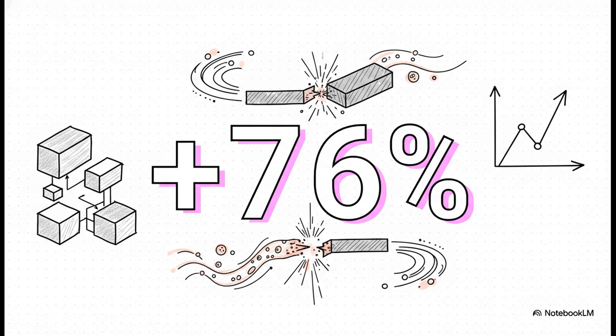In one study, researchers took 3D printed aluminum, used a very thin copper layer during the weld, and then applied specific heat treatments afterwards. By carefully controlling how those copper atoms diffused into the aluminum after the fact, they could actually fine-tune the metal's internal structure, making it way stronger. That is a game-changing improvement.